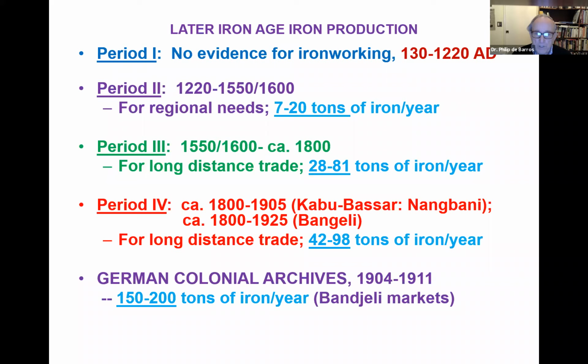And I estimated from converting slag to iron, without going into detail here, up to 20 tons of iron per year. And then beginning in the mid-16th century, we see a rapid increase in growth, and we get estimated up to 81 tons of iron, four times the amount, with long distance trade beginning, and increasing in the 19th century to almost 100 tons per year. And that's based on archaeological data, and on what I discovered in the German colonial archives. Actually, a Togolese professor gave it to me, that the Germans weighed iron blooms in the marketplace for 7 years and found that they were producing 150 to 200 tons of iron per year.